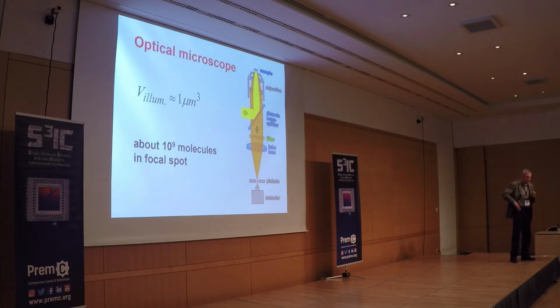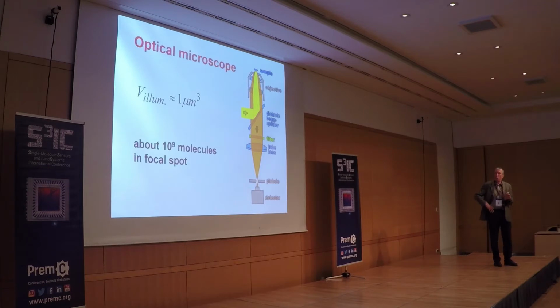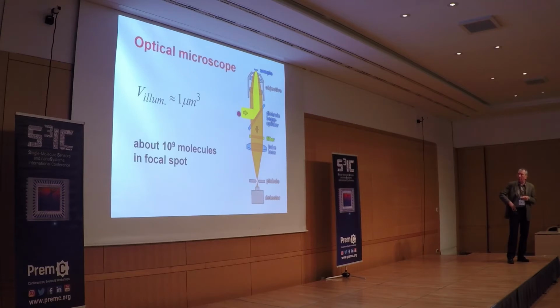So we are doing optical experiments, and basically it looks most of the time like a fluorescence experiment in which we have an excitation laser, so this yellow beam here, which we focus with some suitable optics on our sample, usually on a confocal point. You can also do wide field excitation, but usually it's confocal. And from this point, we collect optical signals, most often in the backward scattered, backward emitted geometry, whereby you can use the same optics for both excitation and collection. That's very convenient. Of course, nothing prevents you from using two different optics, at the cost of more difficult adjustments and more complex setups.